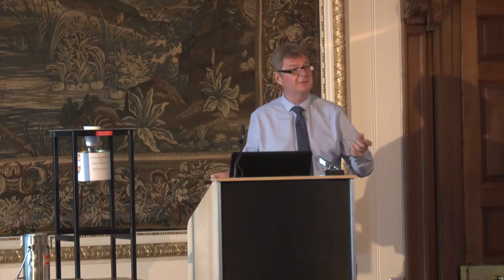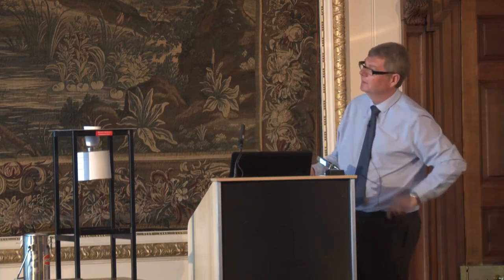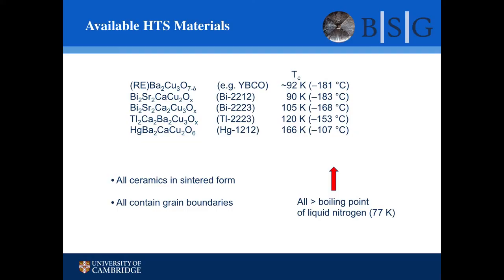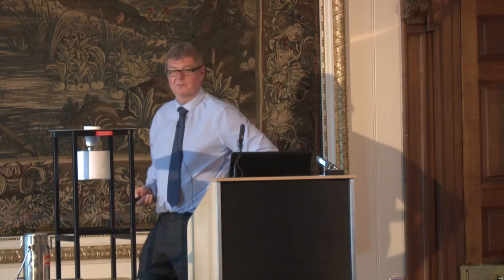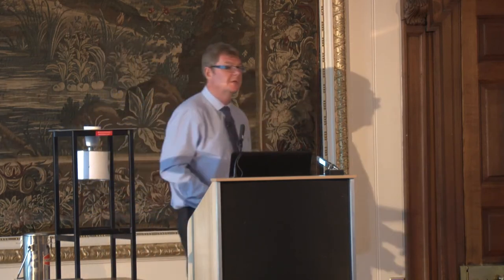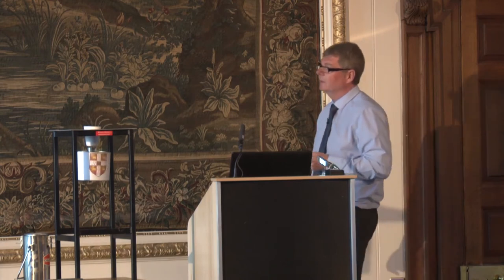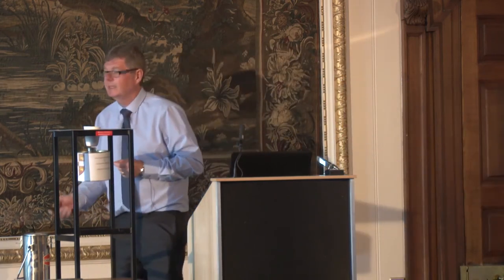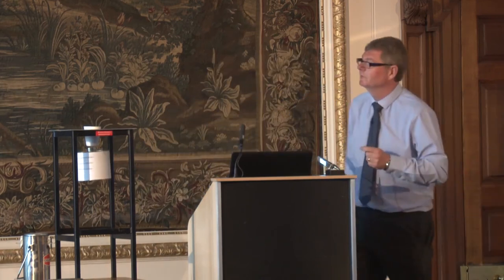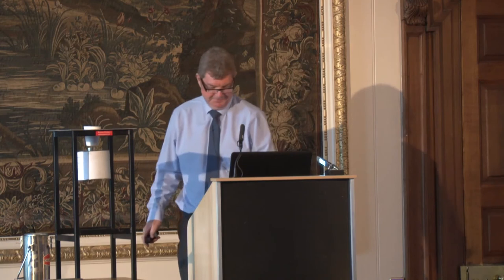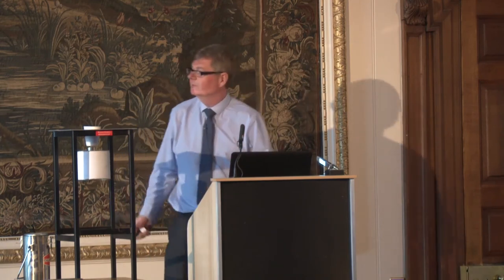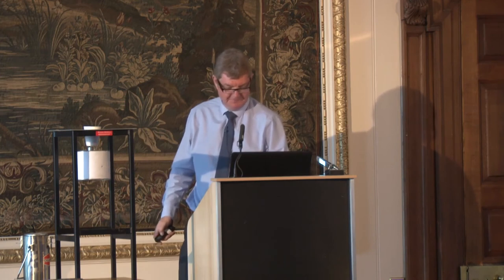But now this BCS limit of 28 Kelvin is looking a little bit tame. And subsequent materials, there's a bismuth-based material, again 90 Kelvin, up as high as 105 Kelvin, a thallium-based material, 120 Kelvin, and the current world record is a mercury-based material of 166 Kelvin. It's minus 107 centigrade. It's not the warmest, but compared to the BCS of 28 Kelvin, it's extremely high. I've got a colleague at the University of Helsinki, and he claims that minus 107 degrees is getting on for room temperature on some days. So people say, are we going to have room temperature superconductivity? My friend Seppo would say we have it already.